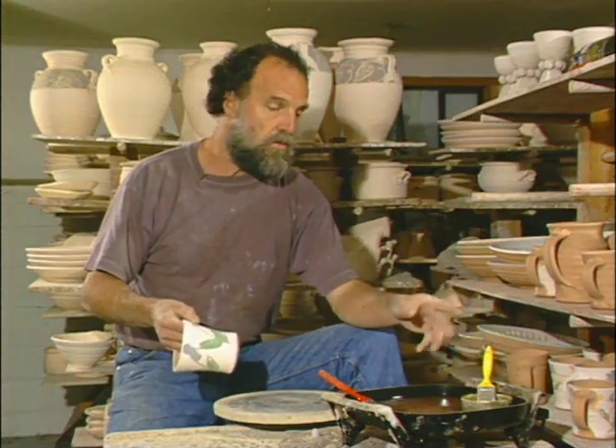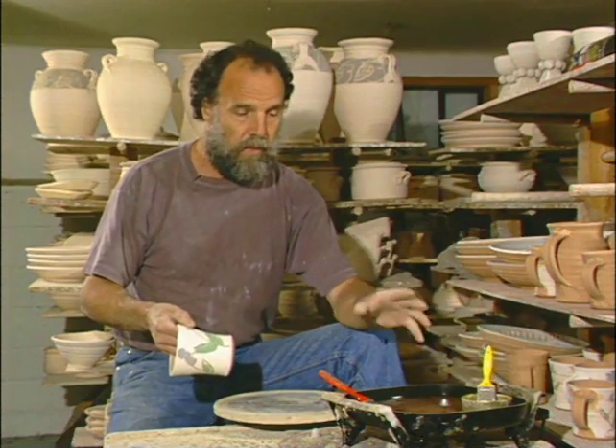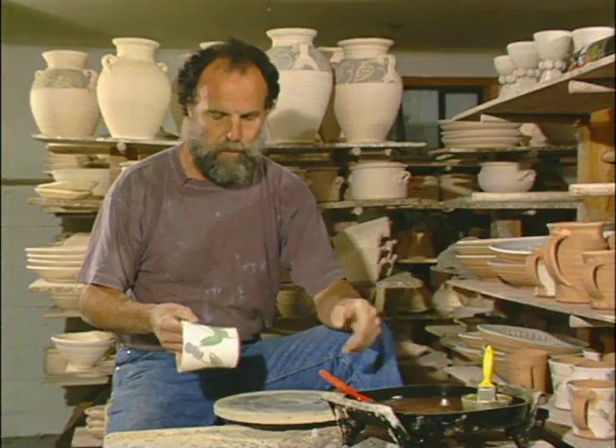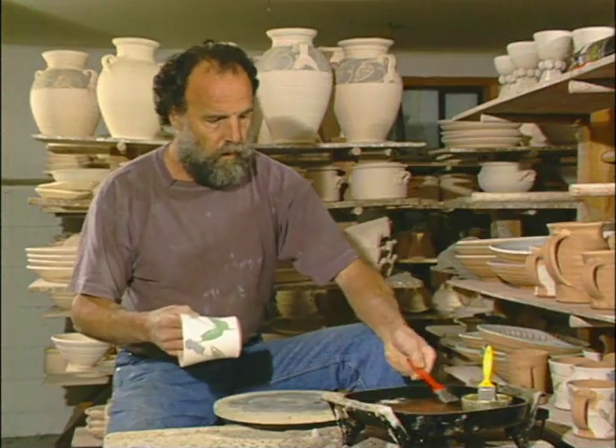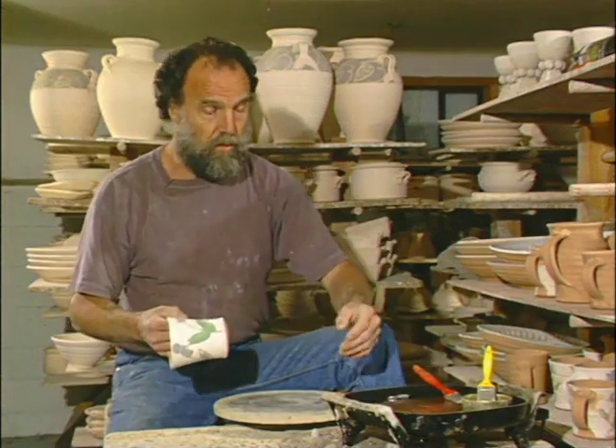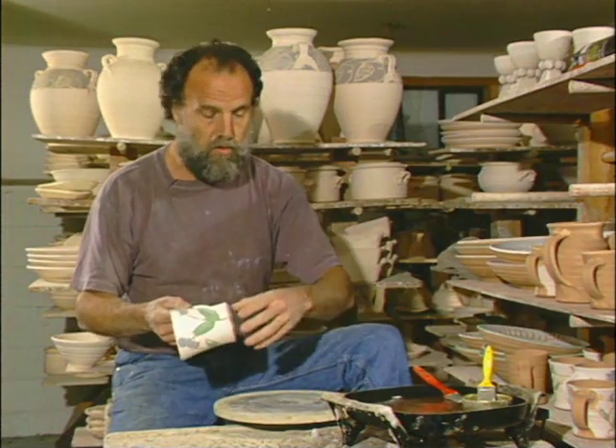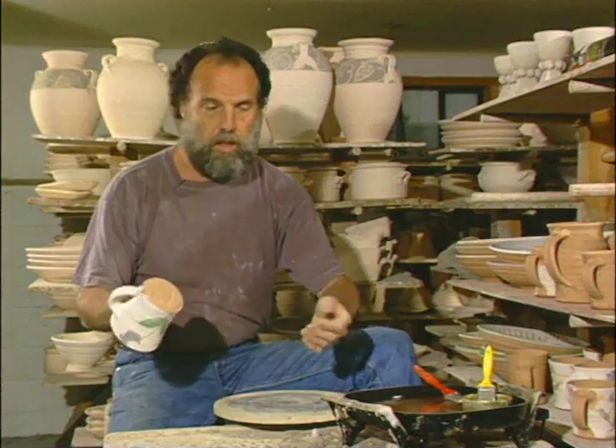Now the thing is, I'm using about 350 Fahrenheit here. The thing is to avoid smoking. You don't want the air to be full of paraffin vapor. Now, this of course is hot, so you've got to be careful, especially if you're working around kids. But this is a very good surface. It's easy to apply, it dries quickly, and it's durable.